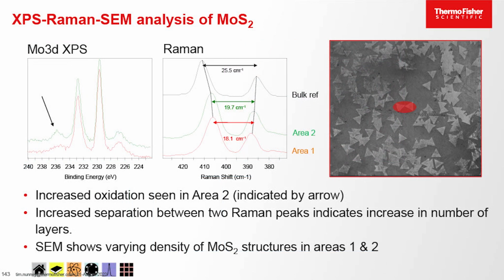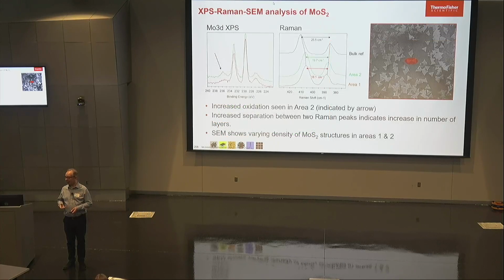Yep. So this works if your sample is conductive, or well on an insulator. Well, if you remember back to James's example this morning with the polypropylene fibers, that's an insulating sample, and so we use low vacuum mode on the SEM, which the way it works on the Axia is that you use some water vapor and effectively use that like the charge compensation system in the XPS. So it ionizes. You are able to then mop up the excess charge that you're putting on the surface.